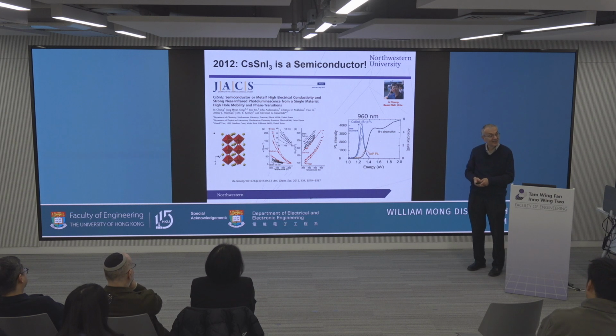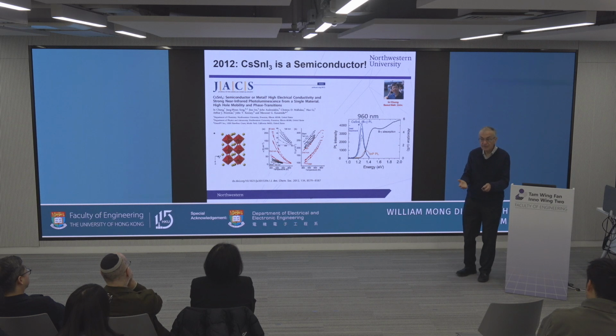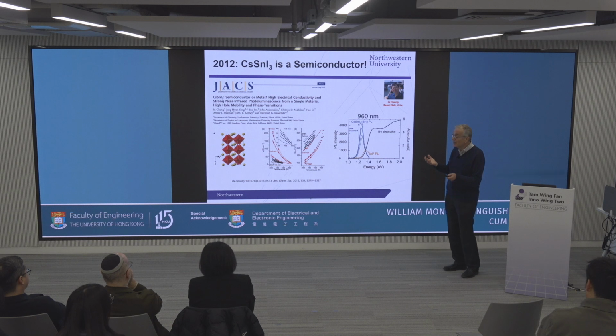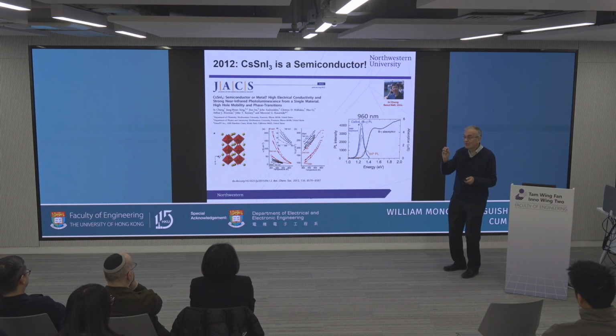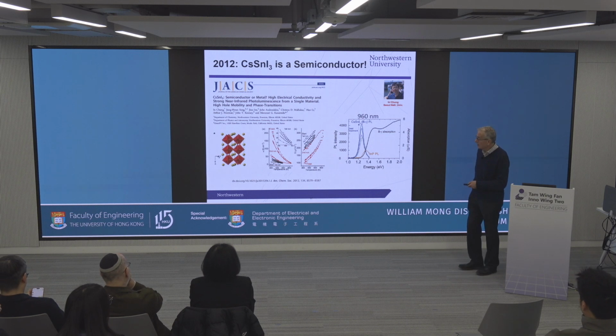So what's happening here? We take an X-ray diffraction. It's not decomposing. It's the perovskite. And what's happening is it's being doped. Some of the tin 2+ is being oxidized to 4+, and introduces holes into the material, lots of holes. And now you have a partially empty valence band and it behaves like a metal.